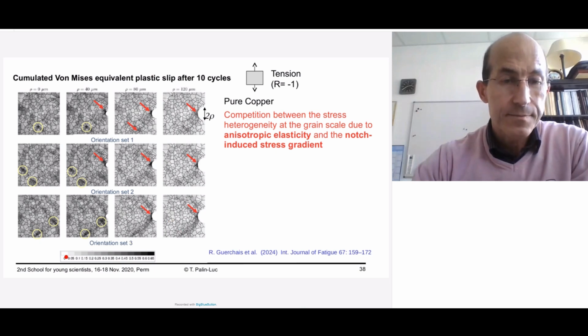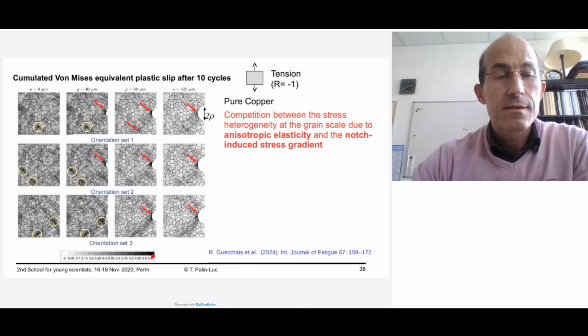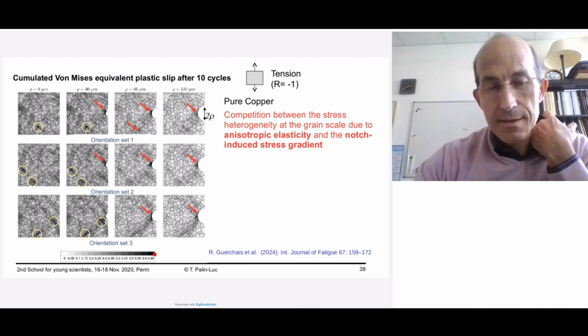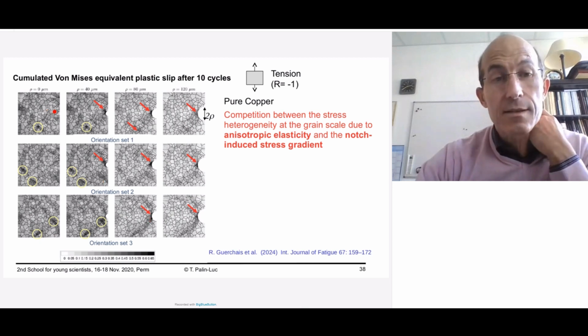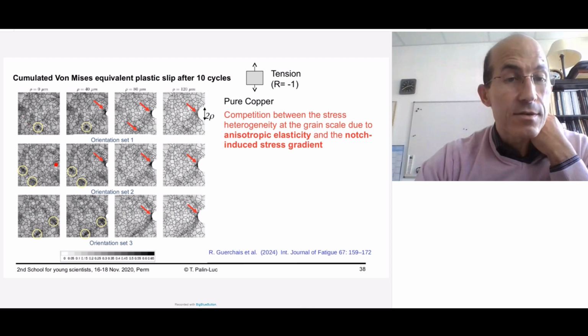So you can see here the different colors, which are proportional to the equivalent cumulated von Mises plastic slip. You can see that when there is no defect, there are heterogeneous colors. So where it is black, this is the highest location of cumulated von Mises equivalent plastic slip. But when you increase the size of the defect, the hotspot is like attracted by the defect. It means the stress-strain concentration is so high close to the defect that there is no microplasticity anywhere else in the microstructure. And this is the same for different crystallographic orientation sets.